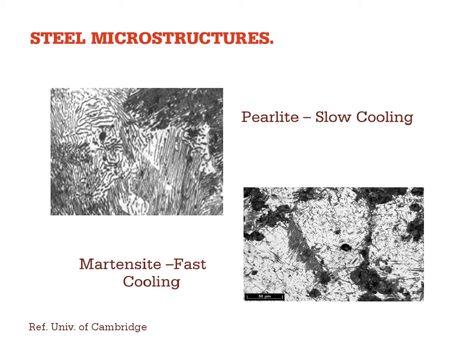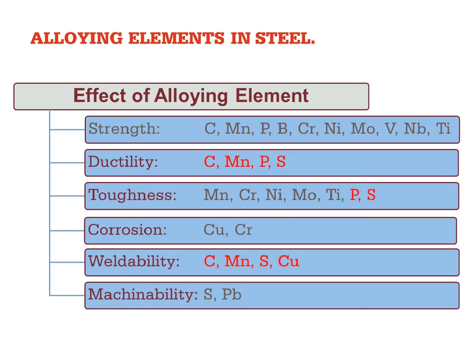And this is dealt with in the heat treatment training course. The mechanical properties and the way in which perlite and martensite will perform in service are very, very different. And it's exceedingly important that we understand that. And we also need to understand the effect of the various alloying elements that I've mentioned. And on this slide, the red ones mean that if you have too much of these alloying elements, they will have a negative effect. So too much phosphorus or sulfur will reduce the ductility and will reduce the toughness, whereas manganese, chromium and nickel will increase the toughness. Weldability is poor if you've got too much carbon. Sulfur again is bad news. So we have to understand the science behind the influence of all of these alloying elements on these various mechanical properties.